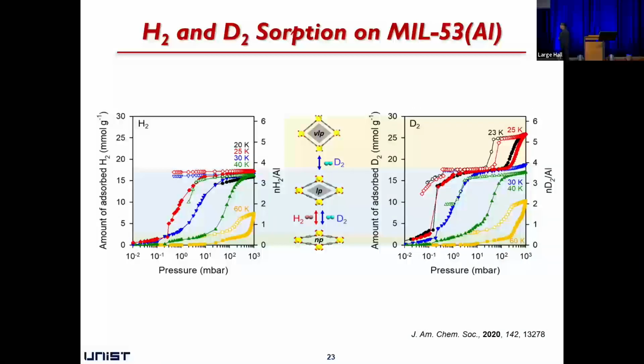3 years later, we examined further for the MIL53. As you can see here, for the hydrogen and deuterium, we can see the clear breathing phenomenon. But in the case of hydrogen, even at the low temperature, we still see the single step breathing phenomenon. But in the case of deuterium, at the low temperature, we already see the first transition, the first breathing. Then we can see the second breathing.